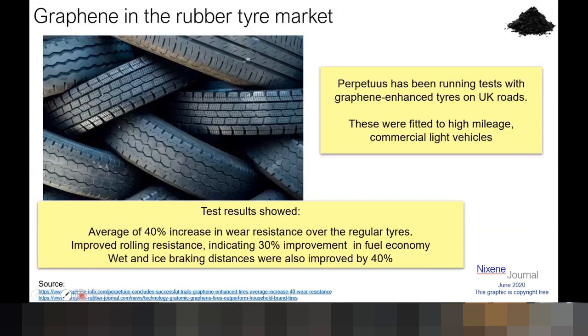Okay, so here's a really good one, Perpetuus, which is a Welsh-based company, so UK-based. They were running tests with graphene enhanced tires. There was an average of 40% increase in wear resistance over regular tires, and improved rolling resistance. As you see there, 30% improvement in fuel economy, and wet and ice braking distance were also improved by 40%. So basically you're creating a winter tire that can be used throughout the year.